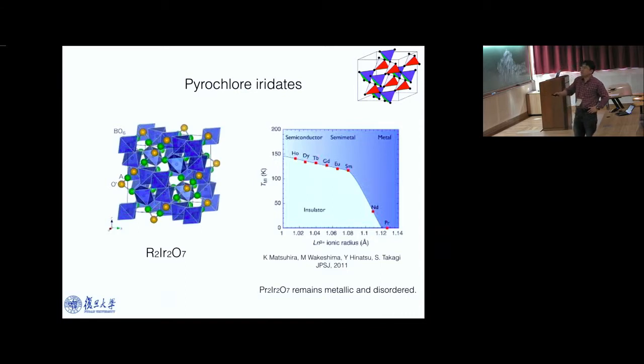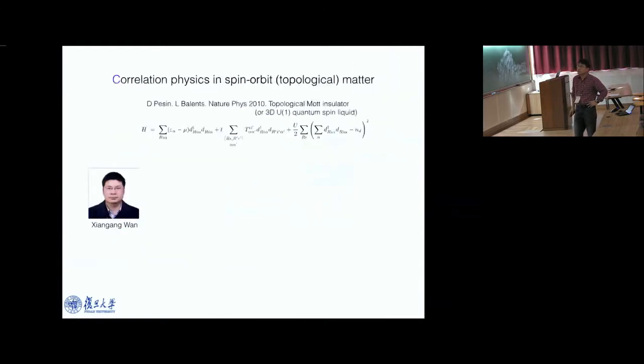This is very different from the other ones, where there is always a metal-insulator transition with some magnetism from the iridium side. Yeah, so let me review some history. Leon Balents and Dmytro Pesin, with a visiting scholar fellow at the KITP, at the time wrote this very interesting paper. They cooked up an extended Hubbard model, including the spin-orbit coupling and the correlation. They proposed this notion called the topological Mott insulator. So this is a very exotic phase.